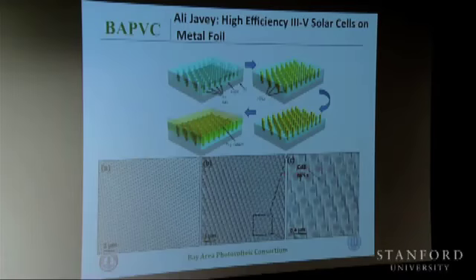Here's one example he grew. This is cadmium sulfide. It's not III-V yet. This is his past research. He tried to extend this approach into the III-V. If you can grow the grain big enough, each of these nanopillars, nanowires is a single crystal. And if you also manage the surface recombination, interfacial recombination right, it might be possible to realize a decent efficiency on a low-cost substrate. So we see if this idea really works. It's possible this type of idea can be transferred to the industry and go into manufacturing with some modification.